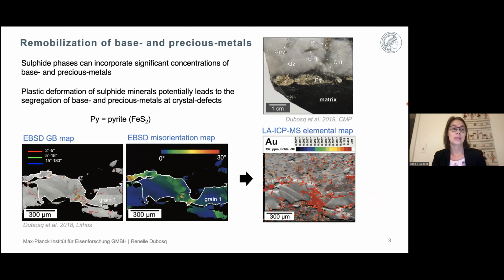In metallic ore deposits, it's well known that sulfide phases, for example, pyrite, which is an iron sulfide mineral, can incorporate significant concentrations of base and precious metals within their crystal structure, either as solid solution or as ultrafine inclusions. It has recently been suggested that the plastic deformation of these sulfide minerals can potentially lead to the segregation of these base and precious metals at crystal defects.